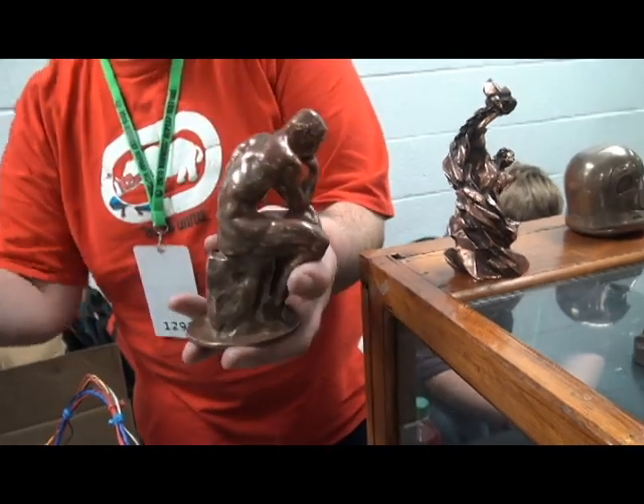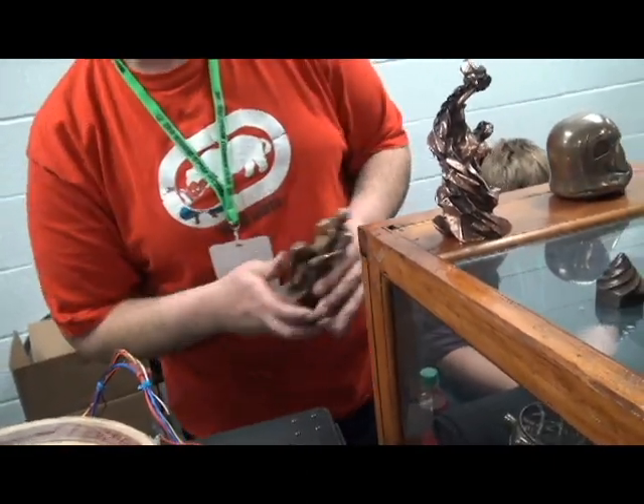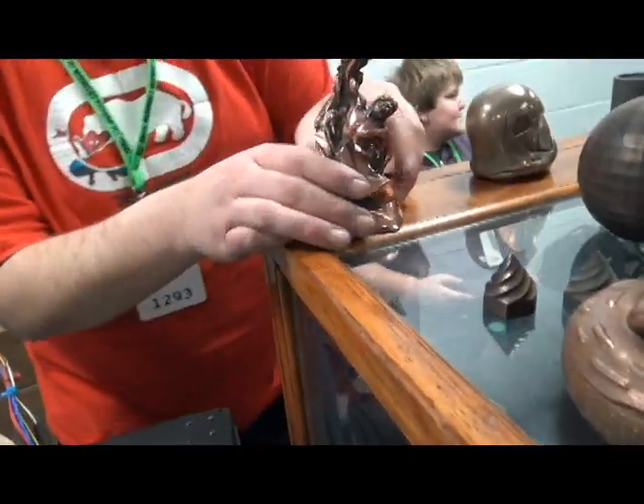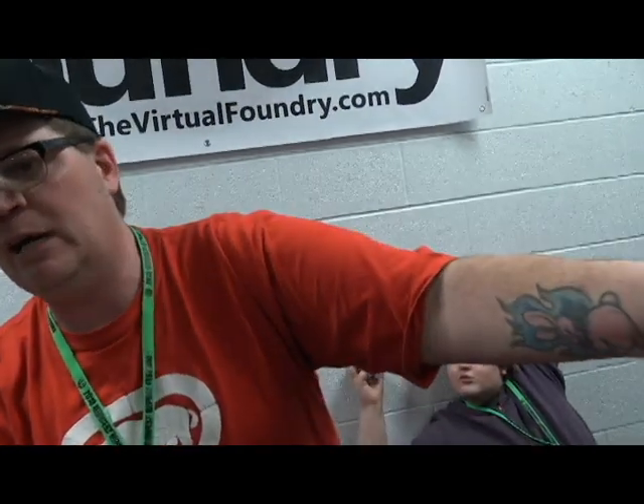Just to prove how bright I could get a shine with that one. Have you tried sandblasting or anything? I sandblast the stuff that I fire, because it has a layer of carbon on the outside after you fire it. The easiest time-saving thing you can do is sandblast it before you polish it up. I do that with the stuff I fire. I haven't really tried it with unfired stuff too much. I like to get in there with my hands, with the elbow grease. I imagine you can get some results with sandblasting and different materials.